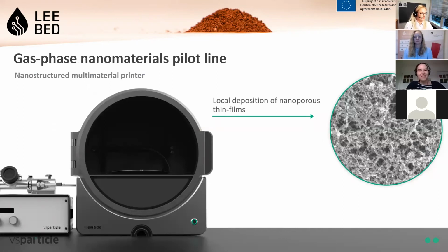So this pilot line is a nanostructured multi-material printer. It consists of a generator which generates nanoparticles from a large variety of metals. And these nanoparticles are in one go then printed onto your substrate, and they form a nanoporous thin film on the substrate. And it's a local deposition method. And so this pilot line is really a system that combines the production and the printing in one continuous process. And this technique is unique.